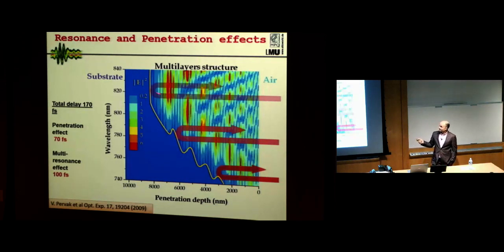We see that these mirrors provide a penetration effect, but when we take the thickness of this coating and calculate in femtoseconds what kind of delay can be provided, we see that the penetration effect provides just 70 femtosecond delay, but if you look at the total delay for these mirrors, it's 170 femtoseconds. It means these mirrors, you can even see here where the hot spots are, have a cavity delay. It means we have a cavity here, here, here, here, here, and here. This cavity provides additional large delay for some certain frequency. Of course, this cavity effect can work just for a certain very narrow band range of frequencies. That's the reason why we have many cavities in these mirrors.